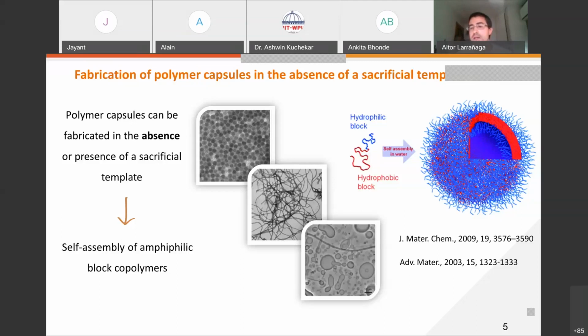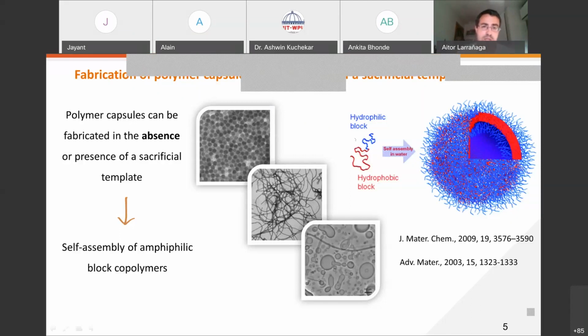And if you think twice, these kinds of structures are really interesting for biomedical applications, because we could simultaneously load both hydrophilic and hydrophobic drugs within this kind of polymer vesicle. The hydrophilic drug could be encapsulated within the aqueous cavity, whereas the hydrophobic drug could be loaded in the hydrophobic membrane. And apart from that, by controlling the hydrophilic to hydrophobic ratio, and also by controlling the self-assembly process, for example, by changing the solvent or the temperature at which we do the self-assembly, we can obtain other kinds of structures other than polymer vesicles that are also really interesting for biomedical applications. And here you have, for example, three pictures of different structures that you can obtain by changing all these parameters, such as round-shaped micelles, worm-shaped micelles, or even more complex structures such as vesicles with gated nanopores.